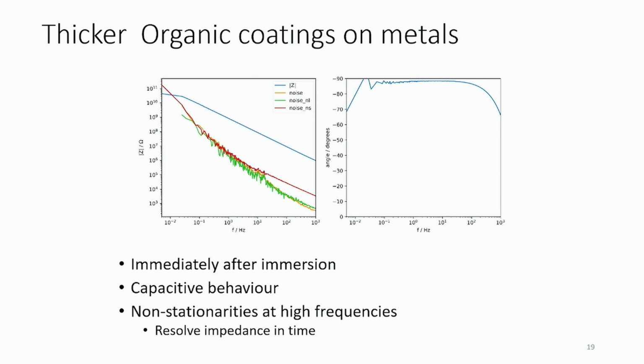If we move now to thicker coatings, you will actually lose the information of the interface in the beginning, because the coating is dominating the impedance measurements, due to the fact that you have a thick coating, which is leading to high impedance. And by the way, here you see at low frequencies that the noise is overruling the impedance information, and this is an indication that at that moment your impedance data become not reliable anymore, because you are measuring so much noise. You see in the literature often high impedances, but they make no sense because you just measure noise at that moment, as we indicated here.